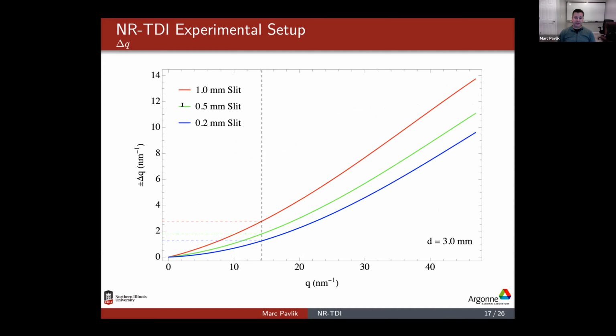So for our 3 slits, if I plot the Q value versus delta Q, this dashed line is that 14 inverse nanometers. This is what that peak is for glycerol that we were using. You can see for the 1 millimeter slit that it has a plus or minus 2.7, which means instead of measuring 14, we're measuring closer to like 11 to 17. And with the smaller slits, the resolution gets better, but the count rate definitely goes down.